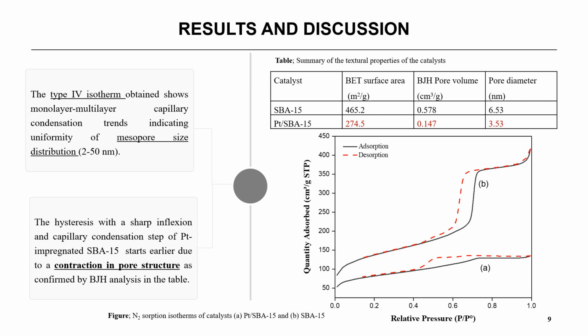However, the sharp and early inflection on the platinum SBA-15 isotherm, in contrast to the SBA-15, is a result of the alteration of textural properties due to the impregnation of metal platinum. From the table, we can confirm this change as we see the narrowing of pore volume, pore diameter, and reduction in surface area. These differences will reflect in a significant effect in the methylation reaction.